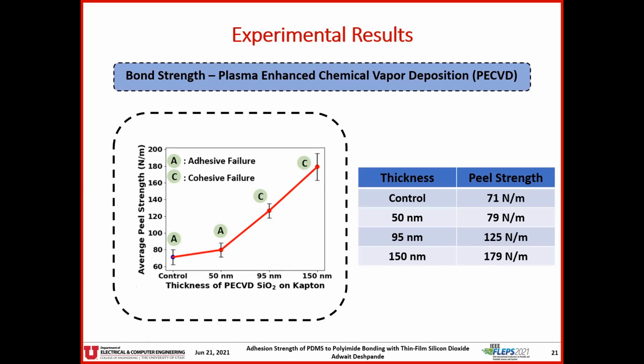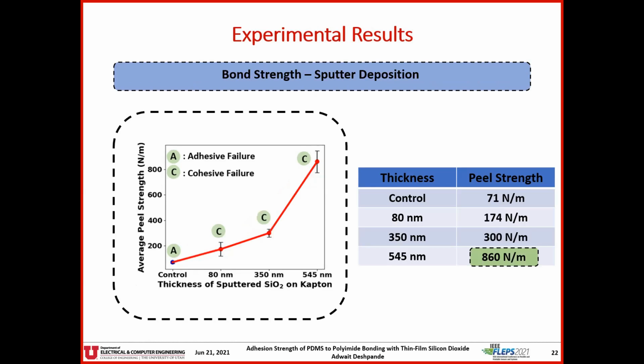All the samples featuring PECVD 50 nanometers of SiO2 showed adhesive failures, whereas all the samples for other two thicknesses showed cohesive failures. For 50 nanometers, 95 nanometers, and 150 nanometers, the peel strengths were 79 newtons per meter, 125 newtons per meter, and 179 newtons per meter, respectively. All the samples featuring sputtered SiO2 exhibited cohesive failures. Samples with 545 nanometers of sputtered SiO2 exhibited average peel strengths of about twice as much as that of highest value reported in literature.